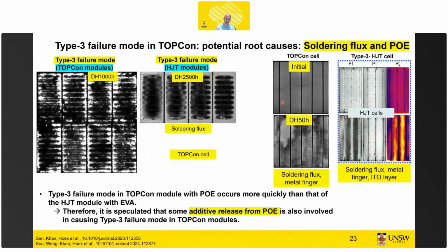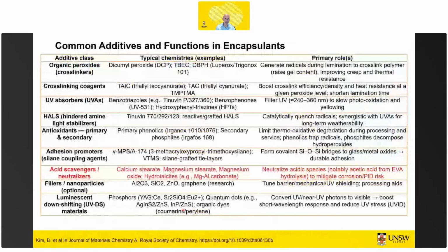But once we tested TOPCon with soldering flux, we did not see the same pattern. So it was not soldering flux by itself. So we speculated that it was an additive of the POE because it was a uniform failure mode. And if it's uniform degradation, the stress factor has to be available uniformly, and the encapsulant is one of them. The glass would be the other, but the encapsulant was, of course, the main difference in the experiment.